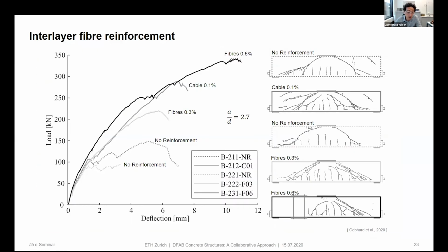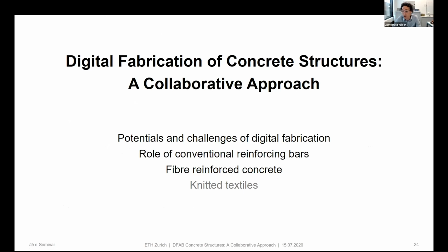Here you can see the results. So of course, when we add the fibers on the cable, we managed to have a good post-cracking behavior. And then you see here in the crack pattern, we have multiple shear cracks. So we were even able to break the cable, so we reached good bond of the cable. So this is promising, but I would like to conclude with a last approach that I think is very interesting, which is how